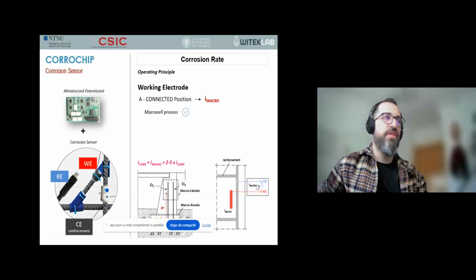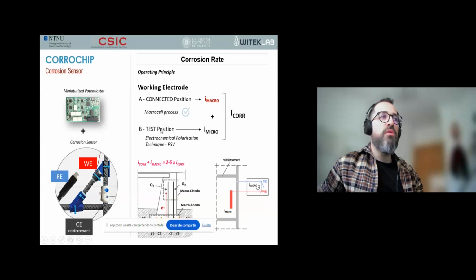The aerial zone, due to higher oxygen availability, demands large quantities of electrons, which are provided by the zone more prone to give them. That's the buried zone, almost in the presence of chlorides. According to different studies, this type of process can accelerate the corrosion of anodic zones up to 5 times. So in the connection mode, the macrocell corrosion current between the working electrode and the structure is recorded. And on the other hand, once a day, punctually, the working electrode is disconnected temporarily from the structure, and the local corrosion current, the microcurrent, is measured by applying the electrochemical polarization techniques. Okay, so the actual rate is the sum of both of them, the macrocurrent and the microcurrent.